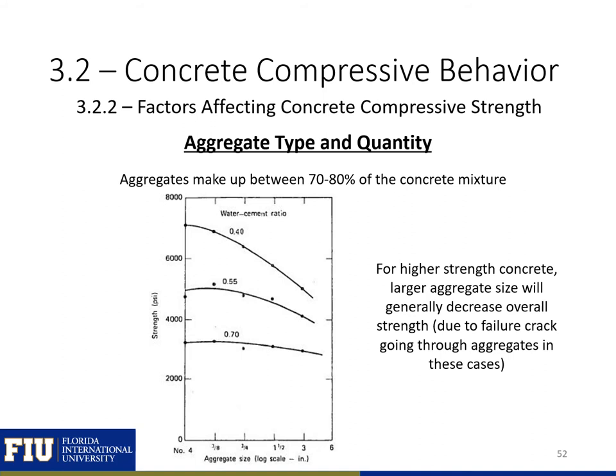The plot here shows the compressive strength versus aggregate size for concrete with three different water to cement ratios. Note that the concrete with a water to cement ratio of 0.4 has the highest strength of the three mixes. Generally, for higher strength concrete, larger aggregate sizes will decrease the overall strength. This is because the failure crack will generally go through the aggregate in high strength concrete, and larger aggregate sizes can result in failure planes with a larger proportion of aggregate.